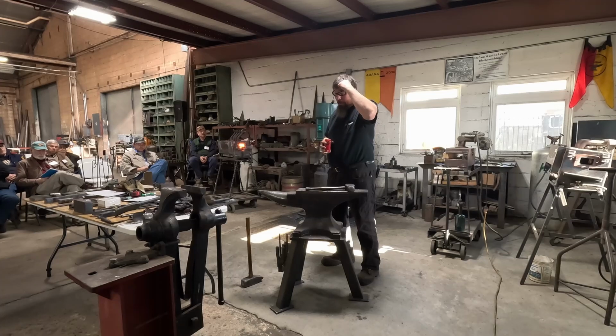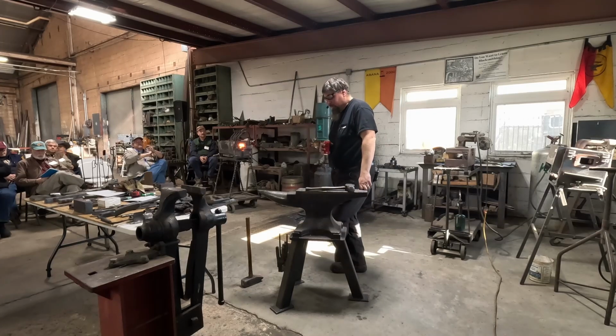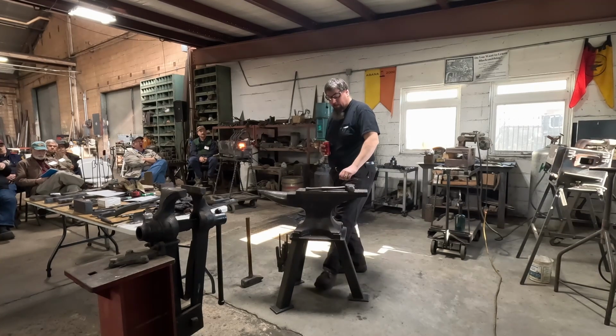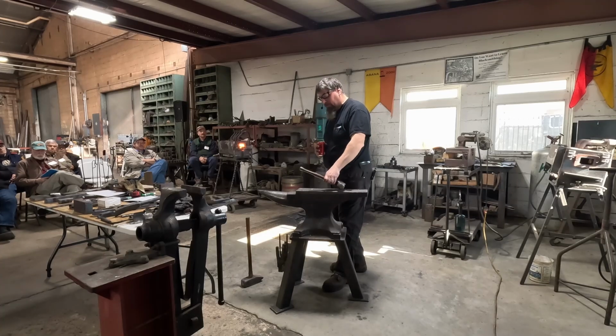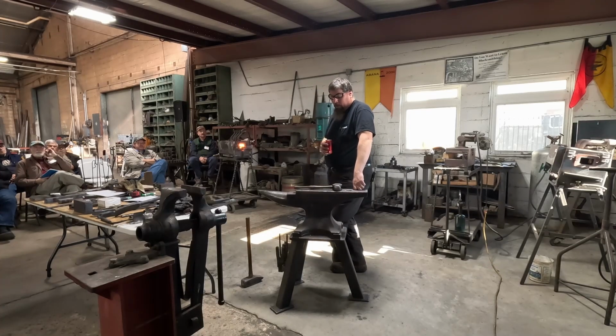If it's a grade that needs to be liquid quenched, if you're dealing with something else, of course, you're air hardened or whatever. But I would say that's probably a minimum, because let's say I have this hammer, for example. This is a little under 5 pounds, 4.5 pound hammer. So I could probably quench that in a 5 gallon pail of water or oil if that's what I needed. But I'd probably only be able to do one. And then the quench fluid would likely be too warm, and I'd have to let it cool down. So if you're doing work at that size, especially if you're doing much of it, you're going to want a larger quench